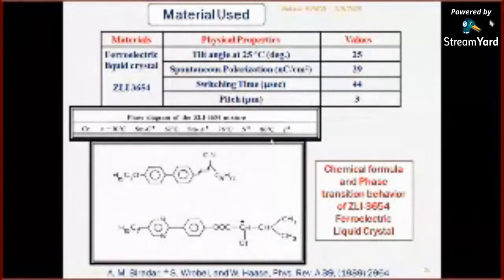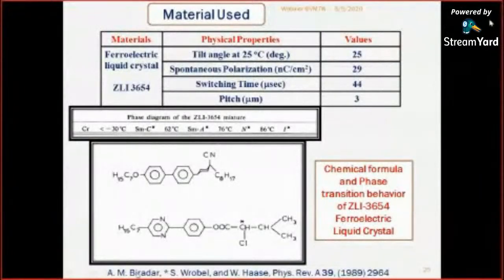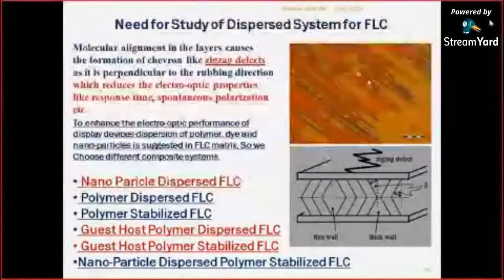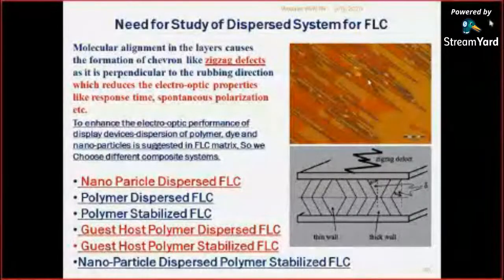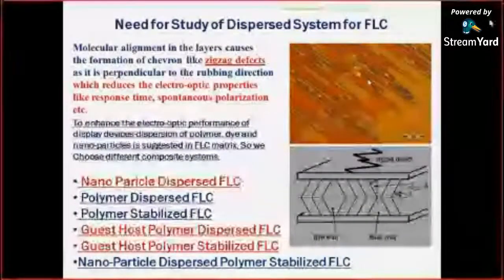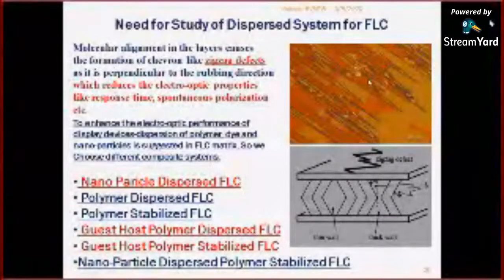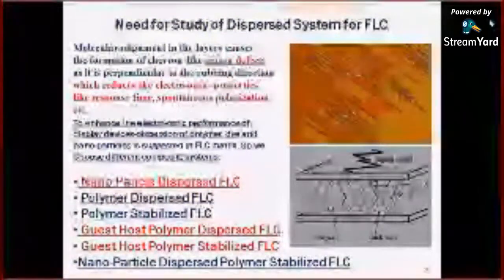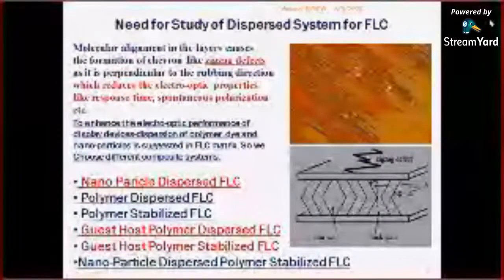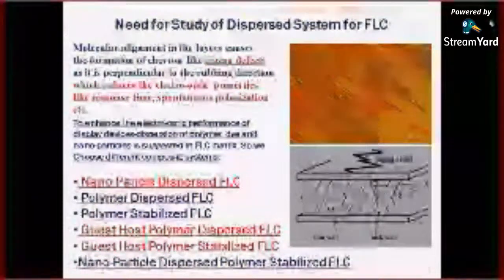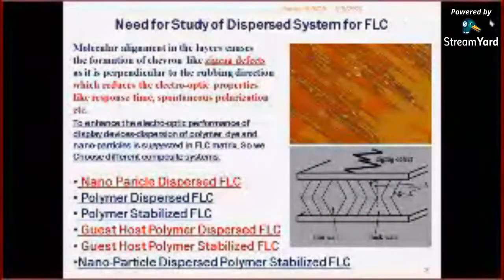And 86 degrees Celsius is the isotropic phase. This phase sequence is given by this paper by Dr. A.M. Biradar in Physical Review A, published in 1989. So this data has been taken from here, and the sample is used for further investigation. This type of ferroelectric sample, which shows the smectic C star phase, has this type of zigzag defect. That zigzag defect needs to be improved by applying some basics of nanotechnology, or by adopting nanomaterial, to improve the response of this sample.